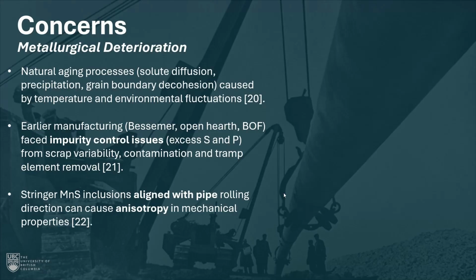One, of course, is as the pipe ages over time due to temperature and environmental fluctuations, we can see processes like solute diffusion, precipitation, or grain boundary decohesion. And this can express itself as precipitation in terms of carbides or manganese sulfide inclusion present, which can act as either stress concentrators or trap sites for hydrogen accumulation. Also, as I mentioned, low control over impurities like sulfur and phosphorus, again from scrap variability at the time, contamination, and low trap element removal.